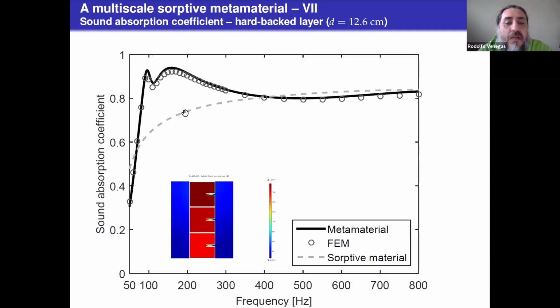In practical terms, what we could get is that instead of having this sound absorption coefficient shown in gray, we can combine these two effects of resonators and sorptive material to get a much higher sound absorption coefficient, starting from about, let's say, 50 to 70 hertz up to 800 hertz. The circles are FEM simulations, and the black lines are the analytical models.